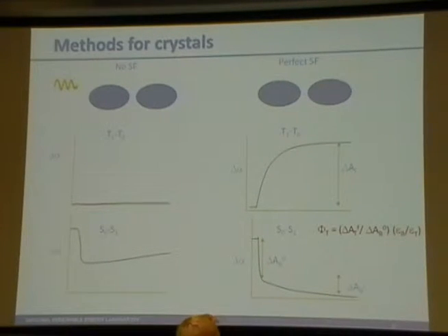So initially you excite the sample, no triplets form, no singlet fission, your triplet absorption stays at 0. But your bleach, which is essentially the S0 to S1, the loss of S0 to S1 oscillator strength, your bleach decreases because as soon as you put an excitation there, this part of the molecule will no longer absorb light at that same wavelength as strongly as it did before. And so that's why you see a loss in that transition. And that happens along with the laser pulse and then decays along with the relaxation dynamics of the crystal.